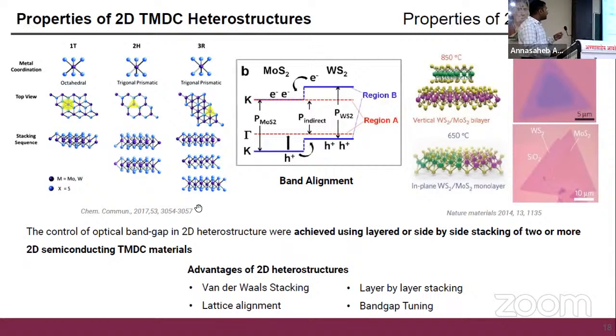Depending on these phases, as I said before, the 2H phase is the semiconducting phase. Using that band structure, we can also synthesize heterostructures of these TMDC materials. Here typically the formation of heterojunction between the band gap of MoS2 and WS2 is shown. The band alignment takes place, and eventually the lowering and extending of band gap can occur depending on the arrangement we are doing for the heterojunction formation.